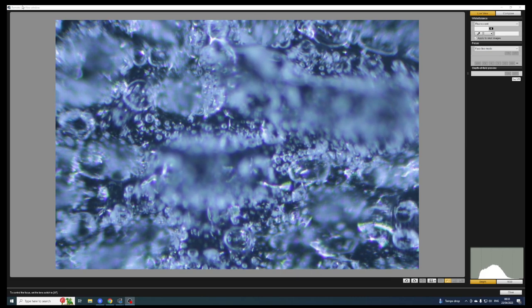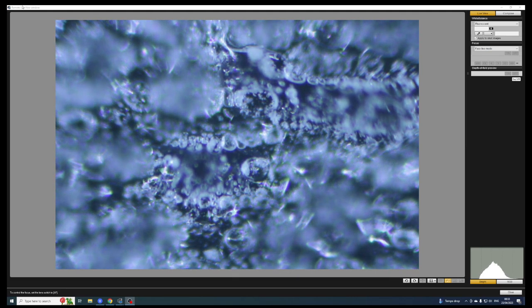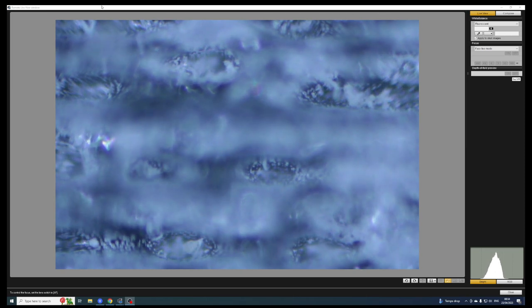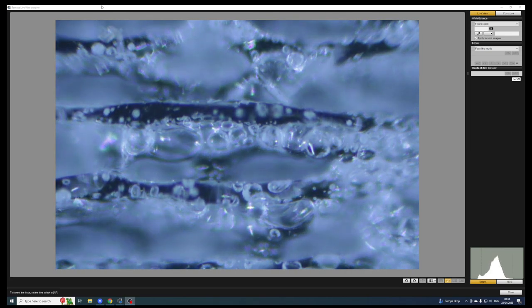And we'll take that in and look at that under the microscope. This is the last one done at 12mm air gap. And as we zoom through the surface and down into the material you'll see we've got lots of bubbles. They're not micro bubbles but they are definitely lots of bubbles there. There's more bubbles there than we've seen before. So let's compare that with 11.5. We seem to have a lot more bubbles on the surface. And as we drop down into the grey hole. Look at us. Look what's on the bottom of the grey hole. Lots and lots of bubbles. So we've actually got a greater density of bubbles there. Different sizes. But the main ones are on that edge there at the surface. We've got lots of large bubbles and they're probably the things that are really responsible for giving us the whiter color.